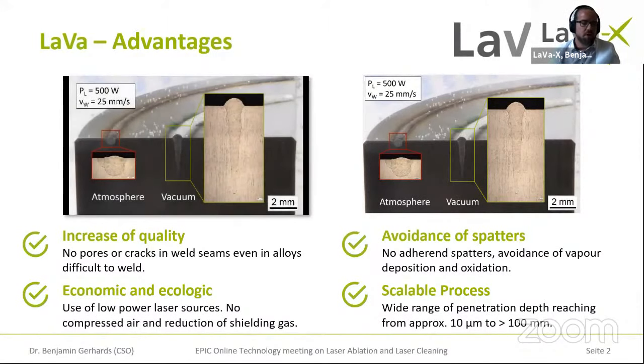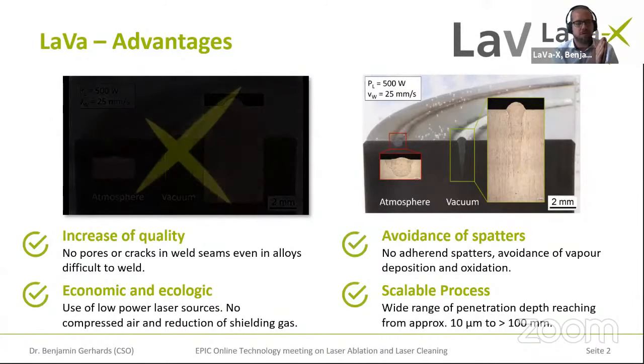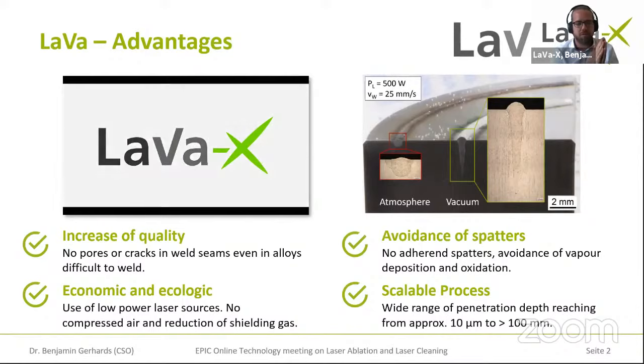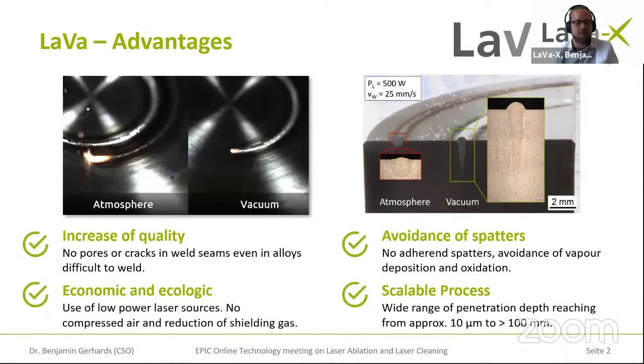So, but we also have several rules of thumb that also apply for the vacuum process. And this is at first the clamping device. So we need a zero gap, nearly zero gap bevel preparation. The gap bridging ability for our process is kind of poor because of the smallness of our beam. So it might pass through those materials that we want to weld without melting them.